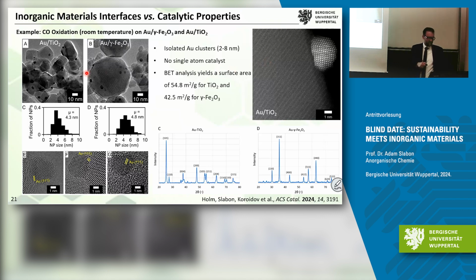We use two catalyst systems, both with gold particles deposited on different supports: here you have maghemite, iron oxide, and titania, with almost the same surface area. You have no single atom catalyst, you have isolated particles. Now, is there any difference if you make the oxidation at room temperature?